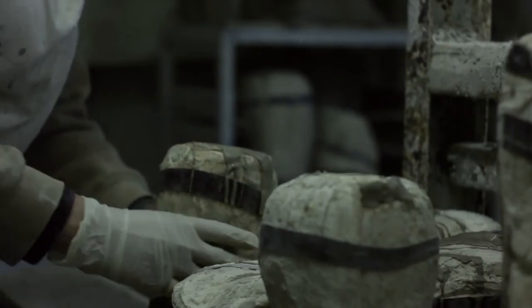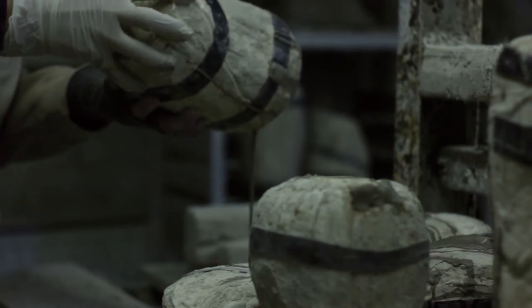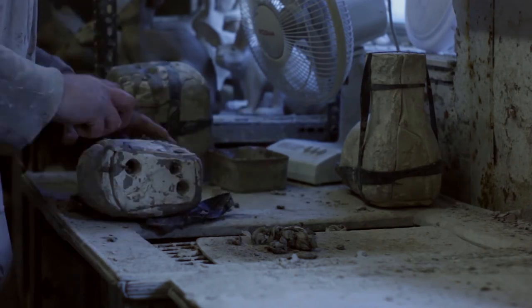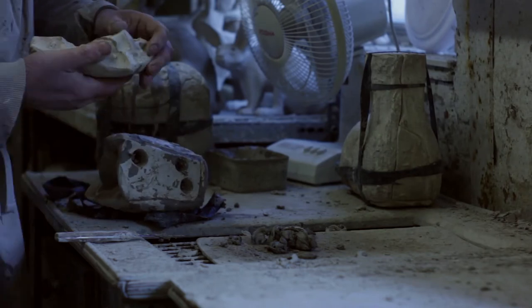Basically the first thing is they have to be cast. They use a plaster of Paris mould — you need the moulds to be plastered because you need both the calcium in the plaster to act as an accelerator and also it draws off the moisture. The mould is completely filled up and left for between 10 and 30 minutes. The surplus slip is poured back out, which leaves a hollow shell casting. They're then left for a few hours to harden up in the mould, the mould is then dismantled, and they're taken out and left for a couple of days to harden up a bit more. They're then knifed and sponged to remove all the joins from where the mould pieces join together.